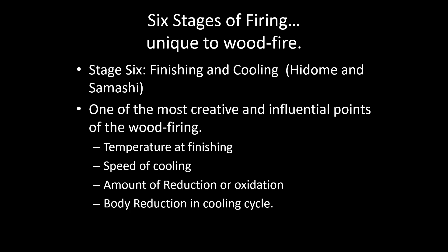The final stage is super important — it's the finishing and the cooling, the hidomi and the samashi. It's one of the most creative and influential parts of the wood fire, because your final results are going to be determined by what temperature you were at when you finished, the speed of cooling, and how much reduction or oxidation. If you cool really quickly, you get glossy; if you cool slowly, it tends to be more matte and crystals can develop. My practice more and more these days is to do a cooling that holds the kiln for a couple of hours at 2,270 degrees — that's the stage where color will be developed in the hiro.